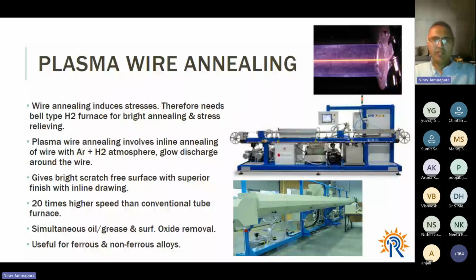So plasma wire annealing involves inline annealing of wire with argon and hydrogen plasmas, and it not only removes the grease, oil marks and oil contaminants on the surface, but it also removes the surface oxides. It gives 20 times higher speed and control than a conventional tube furnace, and is useful for ferrous and non-ferrous, all types of alloys.